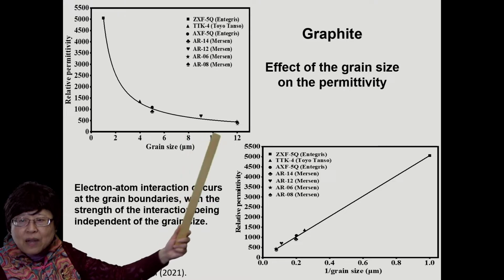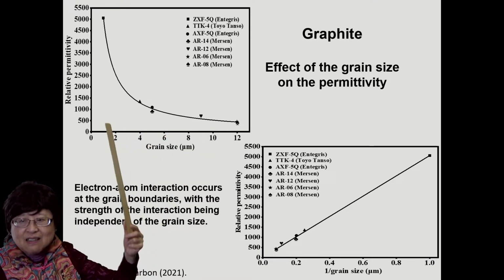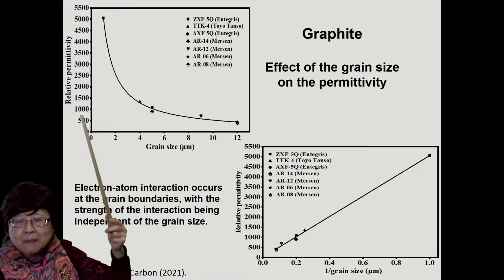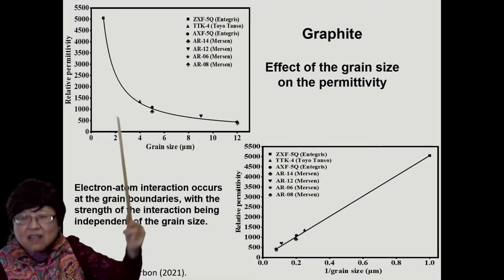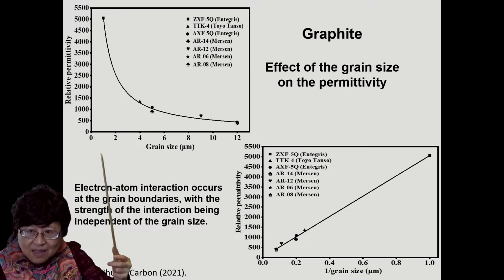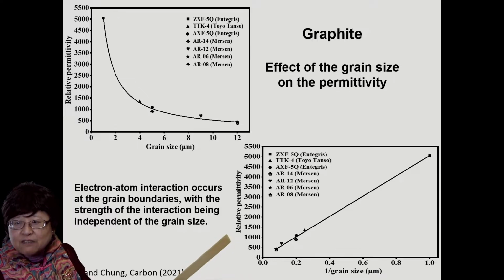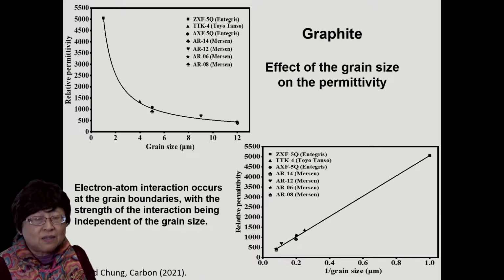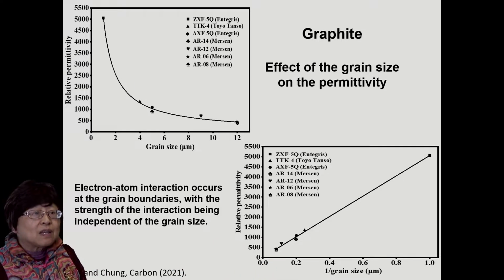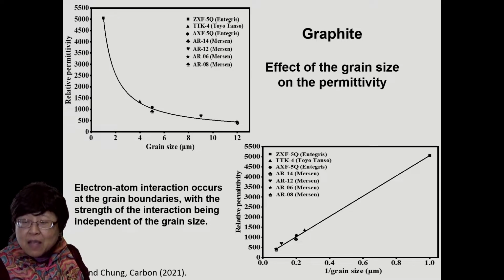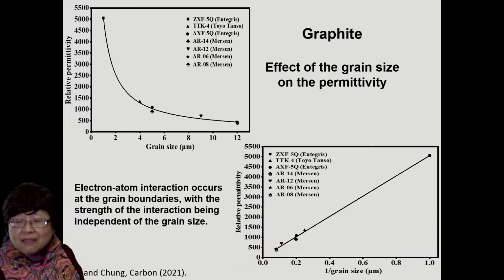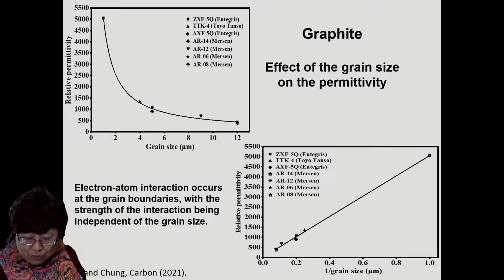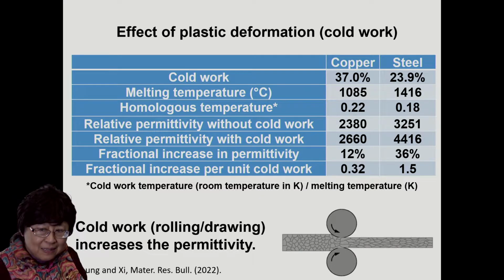And we find that the permittivity increases a lot with decreasing grain size. And we can plot the relative permittivity versus 1 over grain size, which relates to the grain boundary area per unit volume. Then we get a straight line, meaning that the permittivity involves electron-atom interaction, which occurs at the grain boundaries of the polycrystalline graphite.